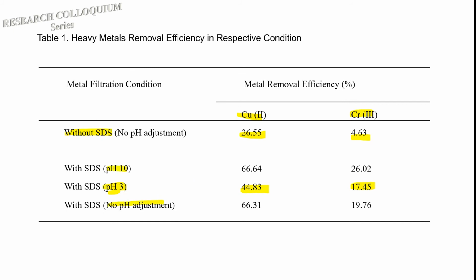This is because at pH 3, usually there will be a presence of H+. So H+ actually is a proton, and for your information, the proton itself is very highly diffusive and hence actually is another competitor to these adsorptions. Eventually, because of the size and the diffusivity of this proton, all those SDS micelles actually are just only bound to this H+, and hence the rejections onto this copper and also chromium will be reduced.